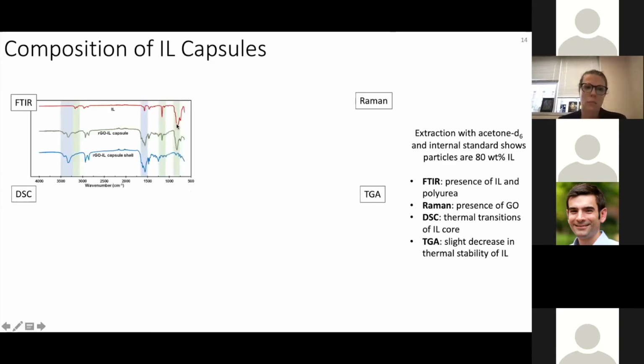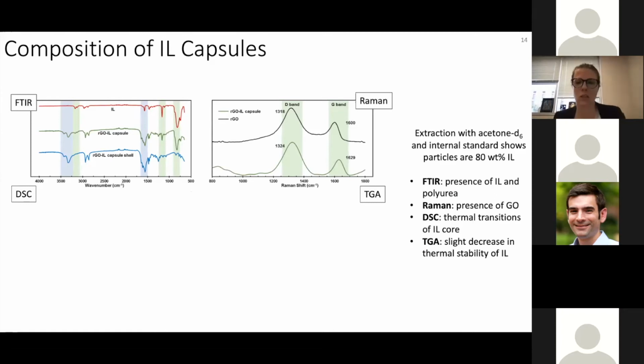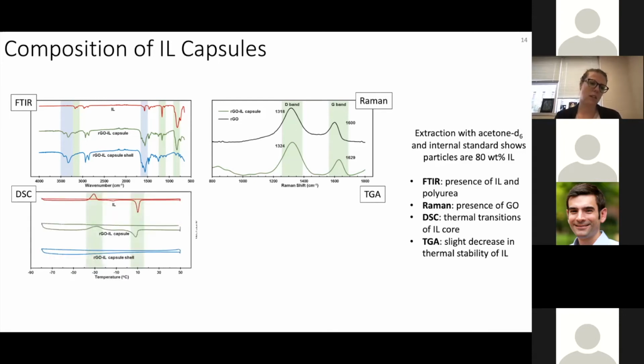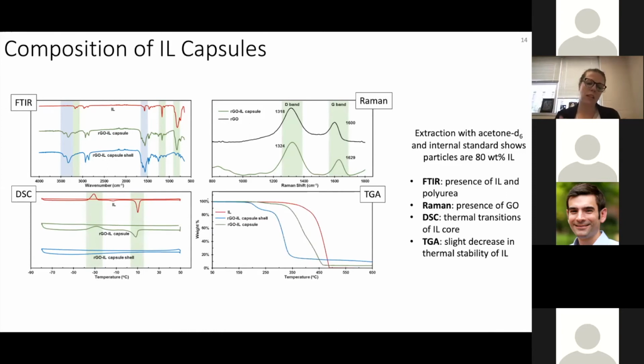We can then compare the FTIR spectra of the ionic liquid itself to the capsules and to the capsule shell, after we've removed the ionic liquid, and we see that we remove the ionic liquid when we expect to. From Raman spectroscopy, we see the characteristic D band and G band of the GO nanosheets, which indicates that the nanosheets are in fact in the shell of the capsule. And from DSC, we see similar thermal transition profiles of the ionic liquid when it's encapsulated as when it's in the bulk. And so this again supports that we have a core of ionic liquid rather than just some polymerization throughout the capsule and ionic liquid plasticizing it. And then from TGA, we see a slight decrease in the thermal stability of the ionic liquid upon encapsulation, but this is common when you mix ionic liquids with anything.